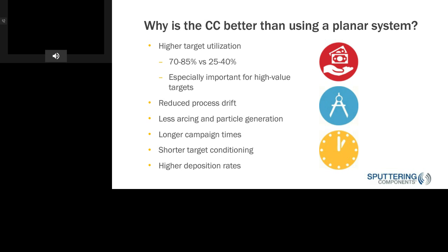And then due to less redeposition at the ends and the target constantly moving, when you're conditioning your target, it will take much less time than it would for a planar target. You also get high deposition rates, and that's because there's more efficient target cooling, higher volume of water is going through there, there's the lower impedance, and it just means that you can allow higher powers, which equate to higher rates.